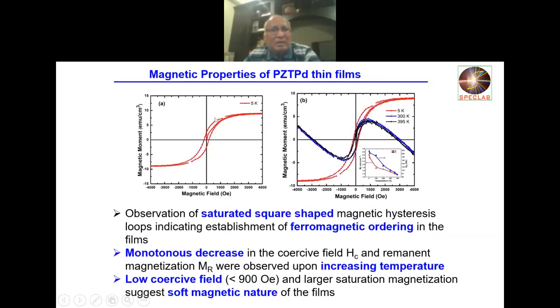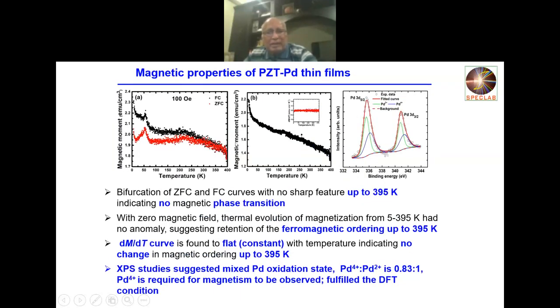Magnetic properties are great. You can see the good magnetization, which is what they theoretically predicted, so that is perfectly correct. And again, talking about the same thing, the thermal hysteresis is flat, there is nothing, no magnetization hysteresis. And you can see when you take dM/dT, it comes out to be flat. So there is no transition at the low temperatures in this material.